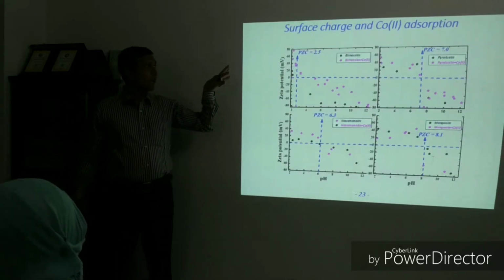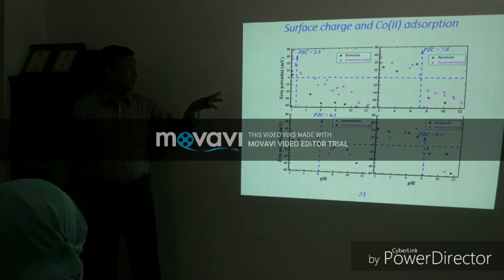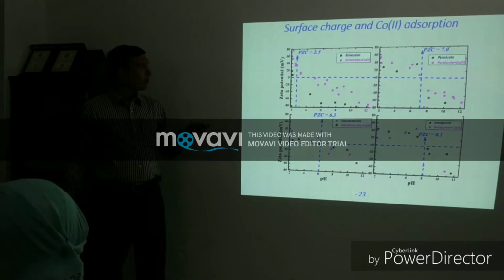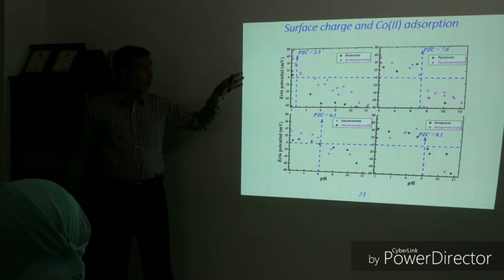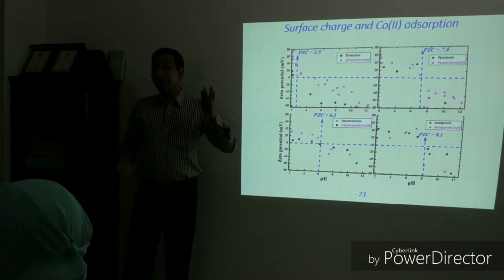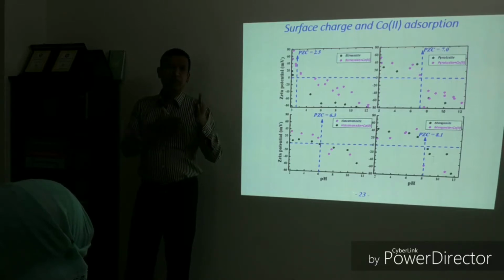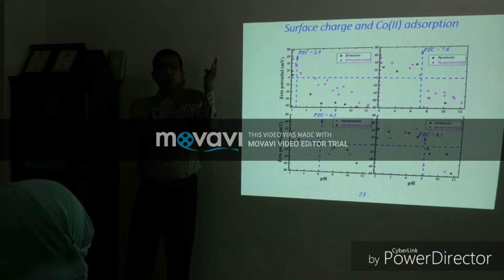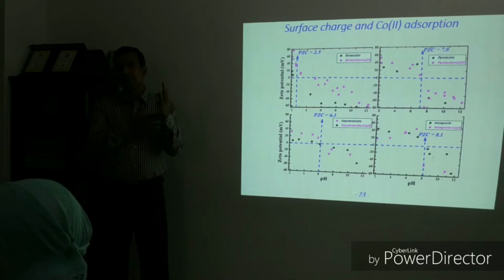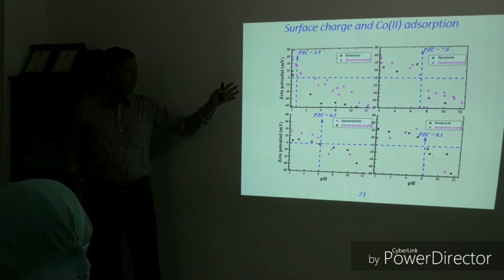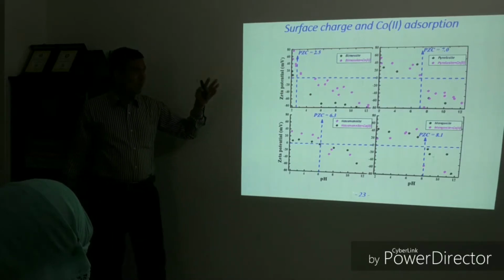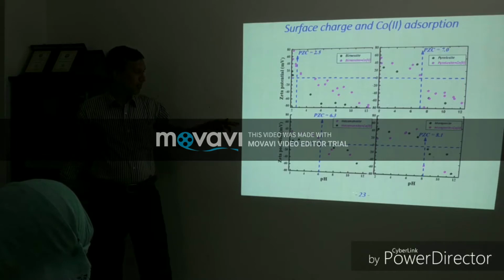Then surface charge and cobalt adsorption. If we see the figure, we see that in the case of birnessite and manganite, after adsorption of cobalt, the point of zero charge has been shifted. Based on literature, only in the case of inner sphere complexation, which is held at the zero plane or surface plane, the point of zero charge or surface charge is changed. On the other hand, in the case of outer sphere complexation, there is no impact on surface charge, which occurred in the case of hausmannite and pyrolusite.